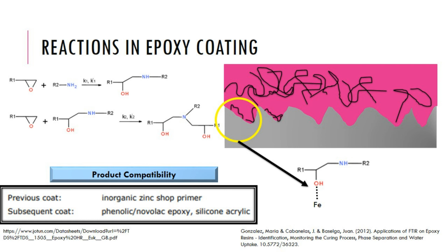But there is also attachment of that molecule to the substrate with the help of weak attraction bonds to Fe. The attraction bonds exist between the hydroxyl group and Fe. This is because of the polarity of the hydroxyl group. Hydroxyl group has a negative polarity, and that makes it attractive to the Fe in the substrate.